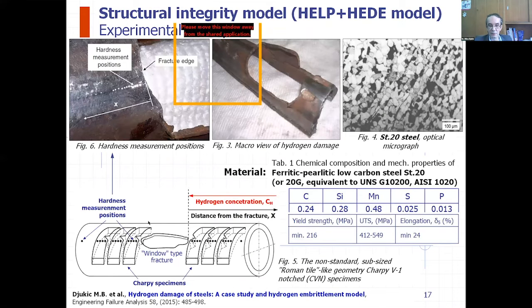So you can see here the position of Charpy specimens at some distance from the fracture, while in the case of the specimen near the fracture feature, window type fracture, we have a very high hydrogen concentration. At some distance from the fracture, we have a drop of hydrogen concentration. You can see here the macro view of hydrogen damage, hardness measurements position.